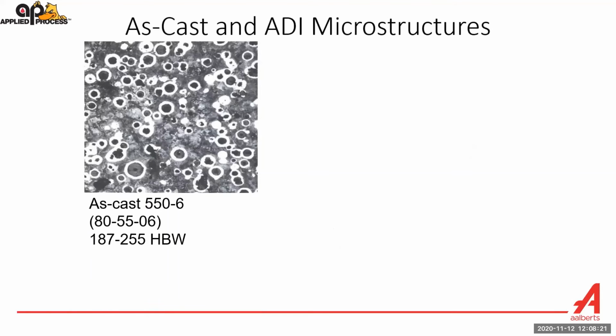So this is what an as-cast ductile iron microstructure looks like. You can see the graphite nodules. They are surrounded by ferrite that's white, and then the medium gray color in between is pearlite. This has a hardness of 187 to 255. This is the most common grade of as-cast ductile iron.